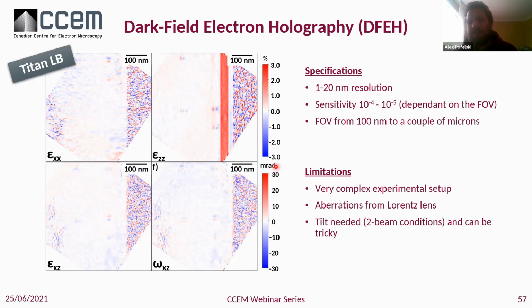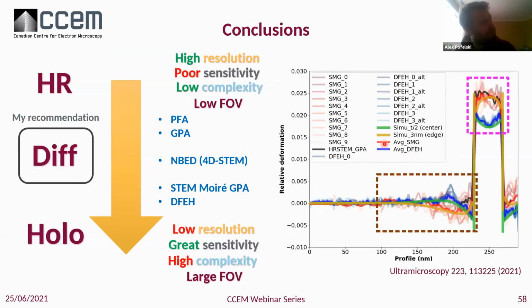So of course, the limitation: very complex setups. You have the aberration from the Lorentz lens, and you have some tilt that is needed. We understood what the limitations are, but after you get very, very nice strain maps, especially very highly sensitive. So that's going to be it for the presentation.